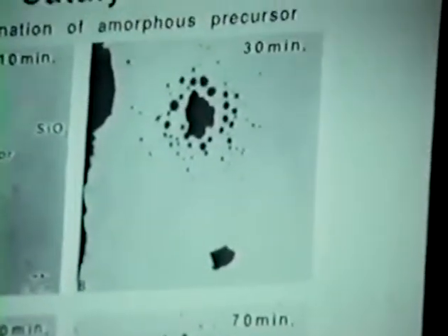Now, this particular particle here was used for focusing and alignment of the instrument, and so it got coated. It was relatively highly exposed to the electron beam, and it got coated essentially with a layer of goo and did nothing for the rest of the experiment. And this was typical of lots and lots of runs. It was only after we started heating, and then when we had reduced the beam exposure to very low levels, that we went to another area and saw that the spreading had begun. And so the precursor initially starts forming these thin discs here through 30 minutes, 60 minutes, 70 minutes, etc. And the difference between here and here is that this large initial clump itself converted into a thin disc.